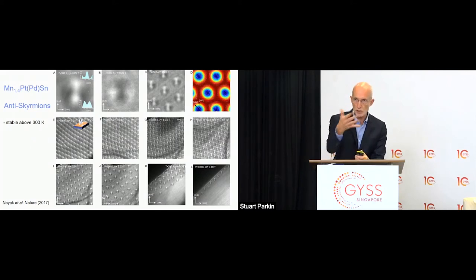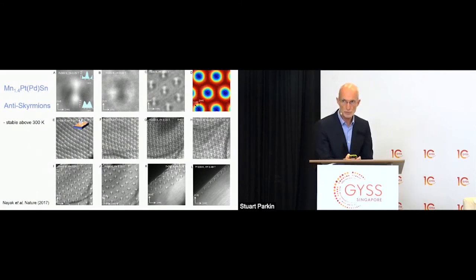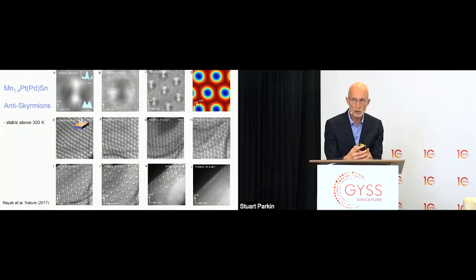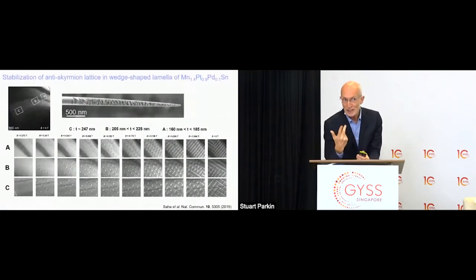Now, it turns out you can also see in E, F, G, H and the rest an array of these skyrmions. And this is typically what you find. You find a hexagonal array of these skyrmionic, anti-skyrmionic objects. Well, this is the first time that these had been observed. That was just 4 years ago. We're very proud of this achievement. And I wanted then briefly to discuss, it turns out these anti-skyrmions have super interesting properties.